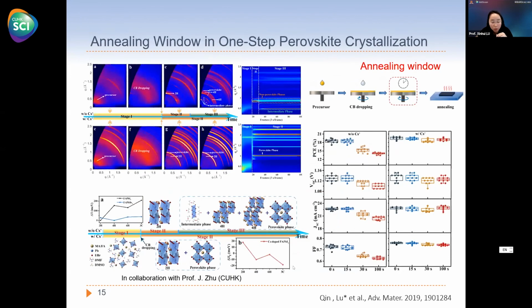So in this work, we are trying to understand, during the one-step perovskite fabrication, when we dope the A-site cation with cesium, or without cesium, what is the crystallization pathway? So without cesium, it undergoes 3 stages, and stage 2 is the annealing window. Stage 2 is very short. So for our device, if we anneal outside this annealing window, the device performance will decrease significantly.